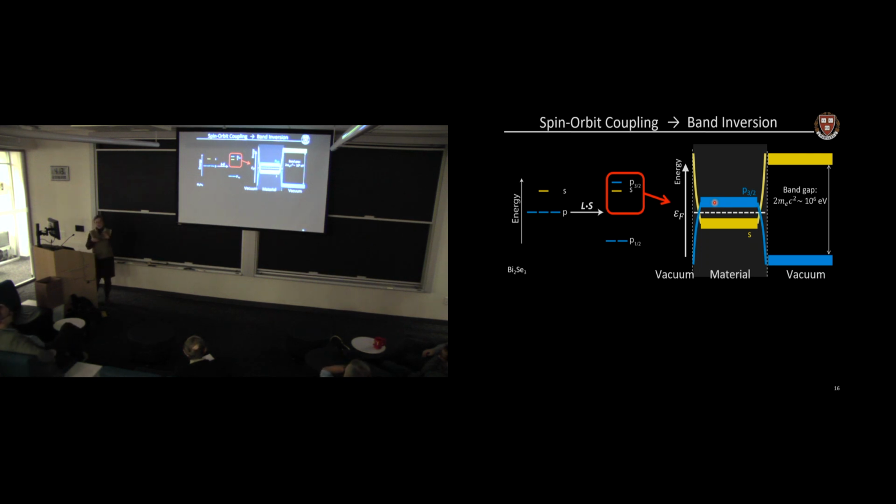And that topological twist, inside versus outside, has to be somehow untwisted at the boundary of the material. And the only way that this twisted gap can be untwisted is to, at the edge of the material, break the gap. So to untwist the gap, it has to be broken at the edge. And what is a broken gap? A broken gap is filled with states.